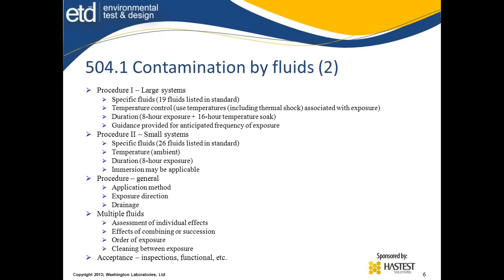For small systems that are typically more handled or mounted into various locations, there are specific fluids, and they list 26 of them, where the temperature is normally done in an ambient condition with an 8-hour exposure duration. Immersion may be the appropriate way to apply this. In general, the procedure is to use the application method of spraying, wiping, or an immersion technique, and the exposure direction. If certain sides are kept away from the exposure to the fluid, they may not need to have the direct application. Also, whatever drainage is provided needs to be provided for this, so you need to be able to get rid of the excess.